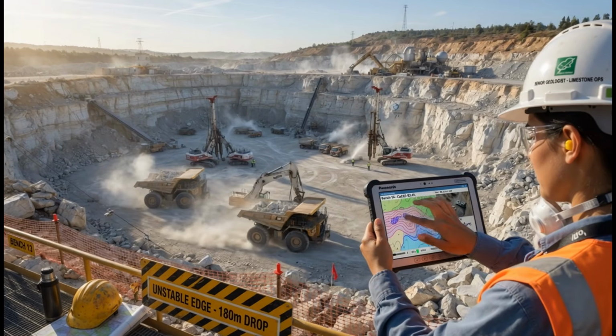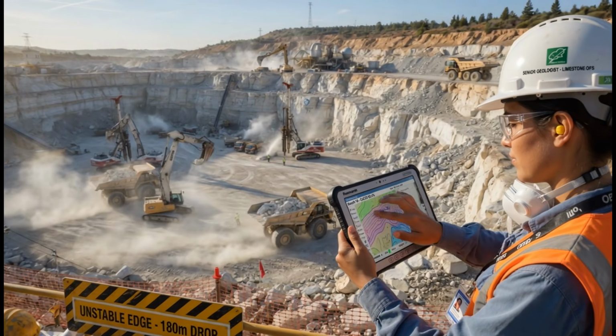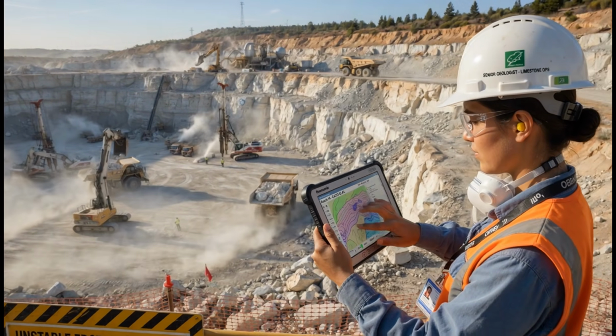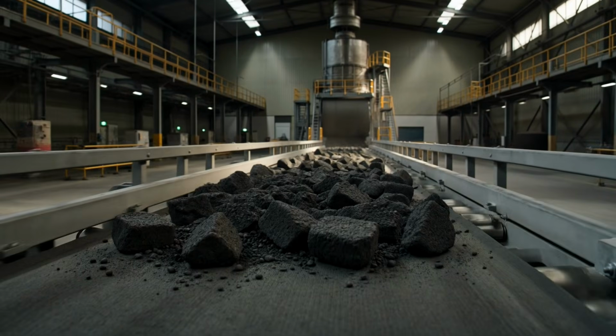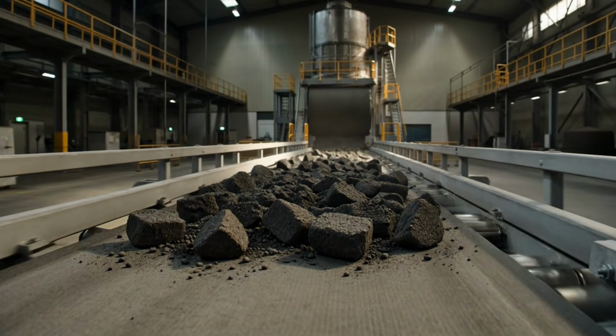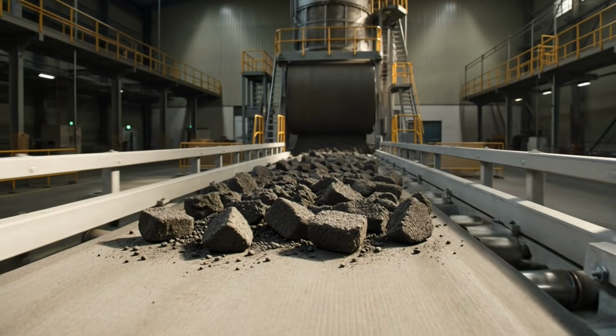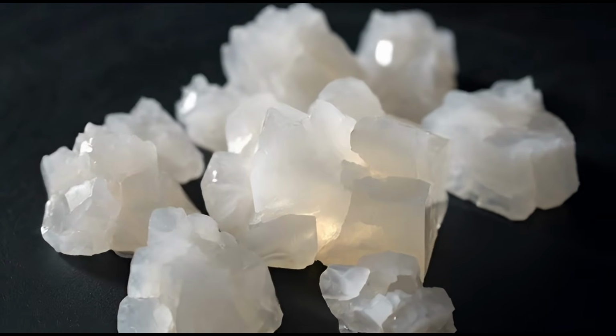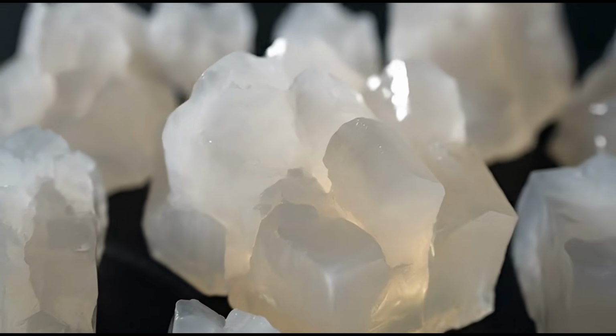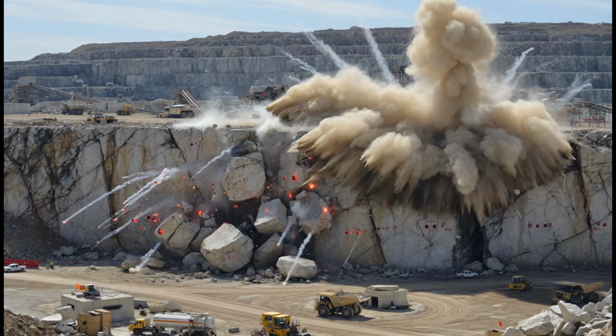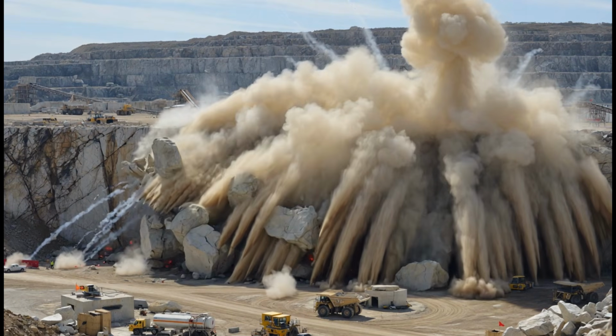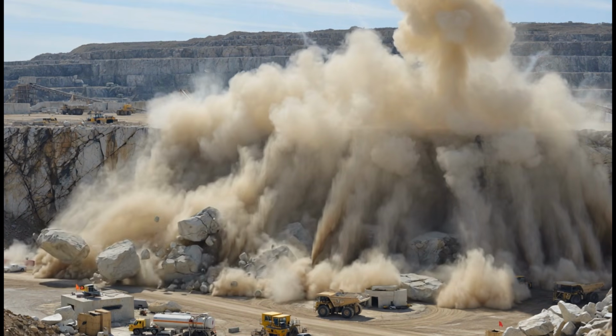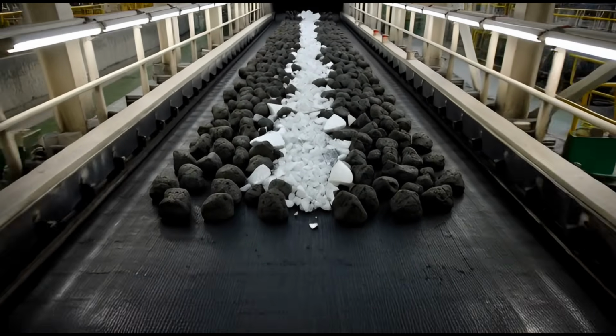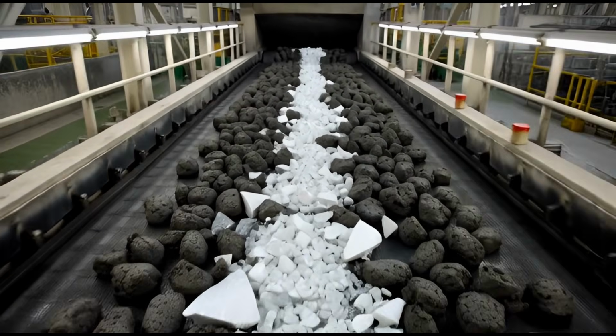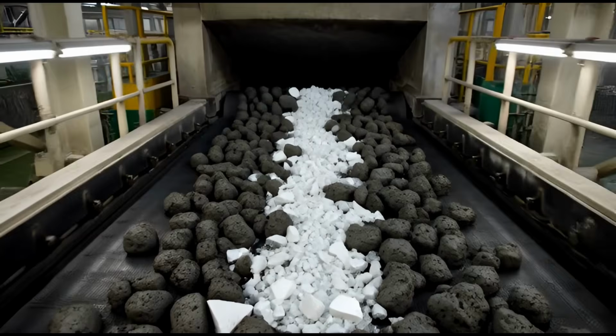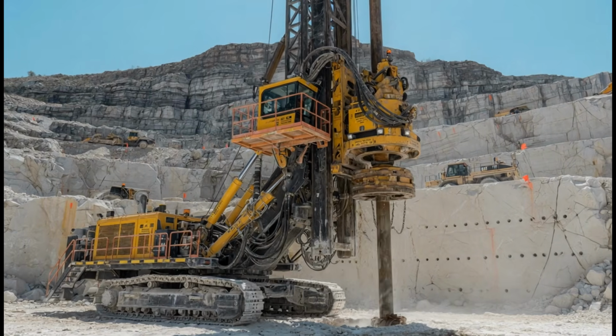But you can't grind clinker alone. One critical ingredient must be added first: gypsum. Without gypsum, cement sets in minutes. Gypsum slows the reaction, giving workers time to use it. Clinker and gypsum go into the cement mill, the most precise stage of the entire process. Inside, thousands of steel balls tumble continuously, grinding clinker and gypsum between them, hour after hour. And what comes out is cement, particles 10 times finer than a grain of table salt.